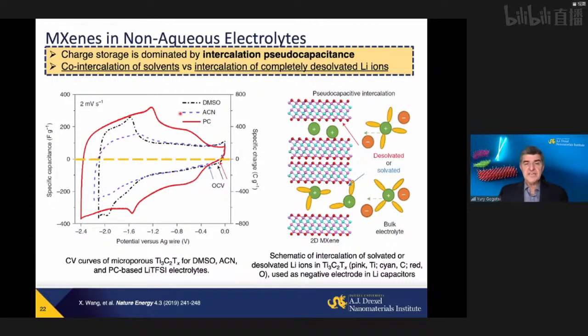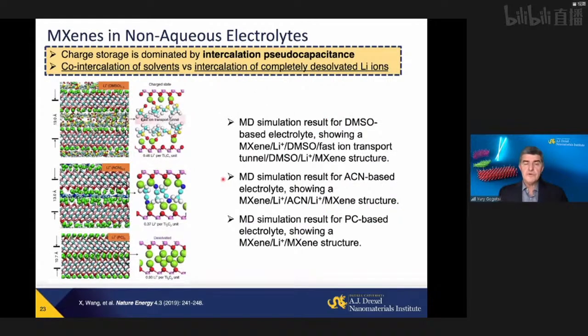And propylene carbonate with an order of magnitude lower conductivity gave us a much larger cyclic voltammogram. So what is going on? What we found is that in the case of DMSO and acetonitrile, lithium ions go between the layers with solvent. DMSO at least has them both on the surface, adsorbed, and mixed inside, so there is fast transport.